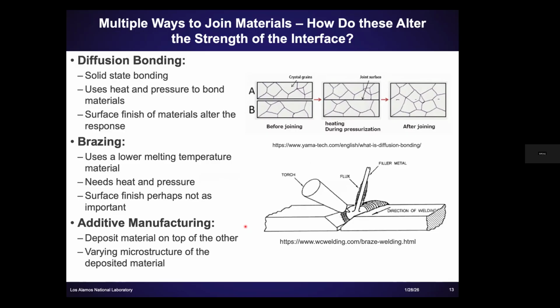There are multiple ways you can join materials together. I talked about welding already. But the two that we focused on were diffusion bonding, which is a solid state bonding process. It uses heat and pressure to bond material. So you can have material A, material B. You clean the surface. You want to have some surface roughness. You put them together, you provide some pressure and you heat it up such that these materials end up joining together and forming an interface. This is one way. Another way, I just call it the metal glue essentially, where you take a lower melting temperature material and put it between A and B, again apply heat and pressure, and the braze material in the middle melts and holds it together, hence my analogy with metal glue.